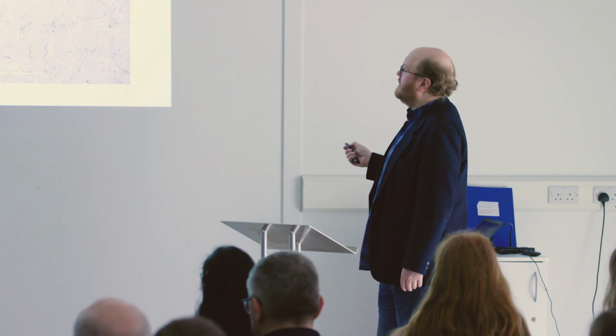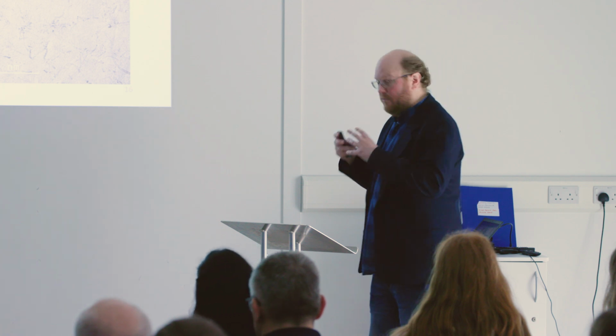The graphene, in this case the GNPs, are very agglomerated together. They're not very well dispersed. They're sticking to themselves more than they are. And so that agglomeration is basically why you need to add a lot of material before it becomes conductive. Whereas the nanotubes, these ones in particular, disperse very nicely, have very high aspect ratio, and that's why they form a conductive pathway very easily.